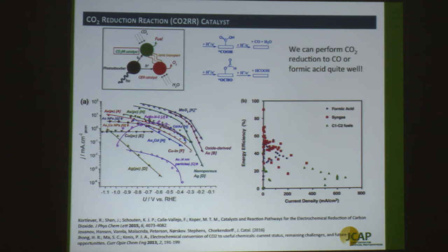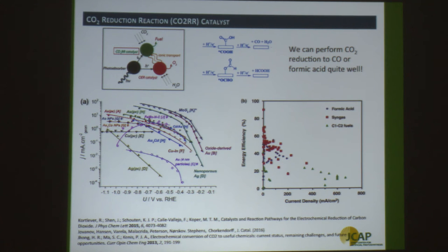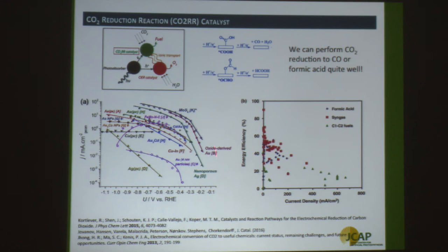The second part of the puzzle is the CO2 reduction catalyst. We can perform CO2-to-CO or formate quite well electrochemically. CO2 is reduced to CO via COOH* intermediate — one proton plus one electron to make COOH*, then another proton-electron step to make CO and water — or via OCHO* to formate. Many material systems can perform CO2-to-CO at near-unity Faradaic efficiency, low overpotential, at tens of mA/cm². We know how to make CO quite well.